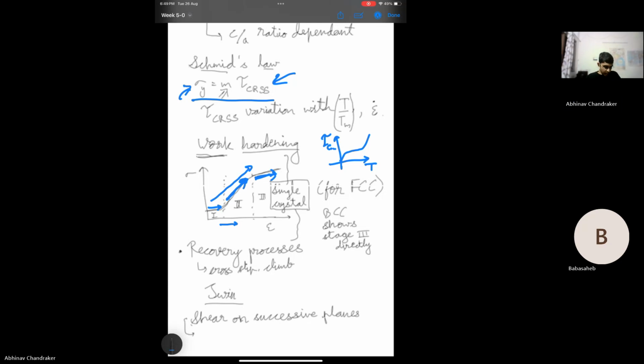Along with that, in stage 3, the dislocations, because the density is high, will start annihilating with each other, which will reduce the density, and they will start forming structures which have lower energy. They will rearrange into maybe cell boundaries or subgrain boundaries, and as a result of these low energy structure formations, the mobility of dislocations will improve because now the tangles are less. You have more definite structures in your material.